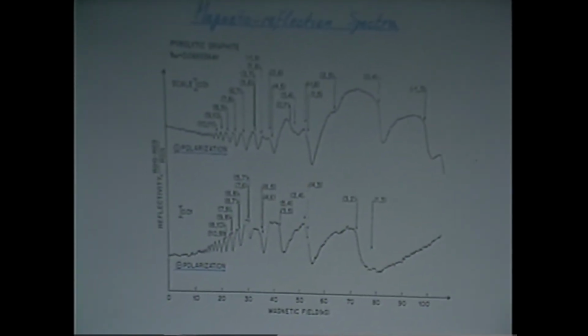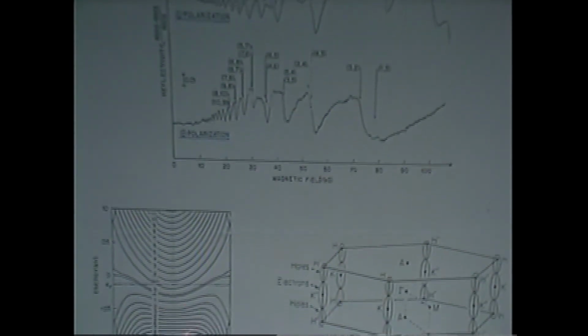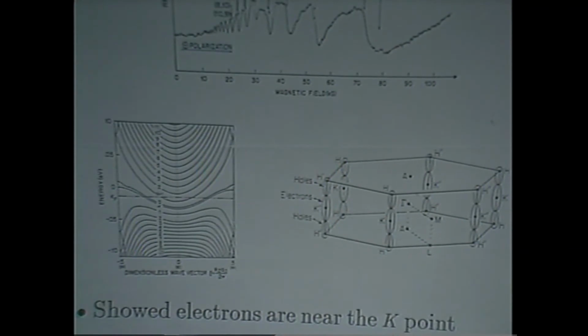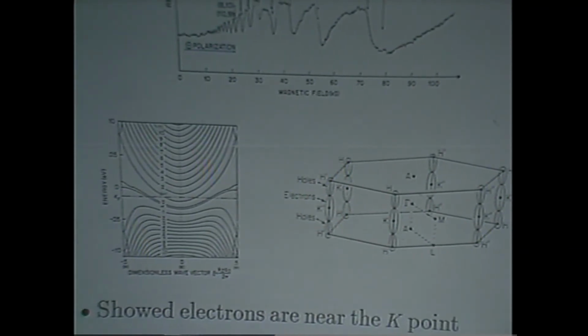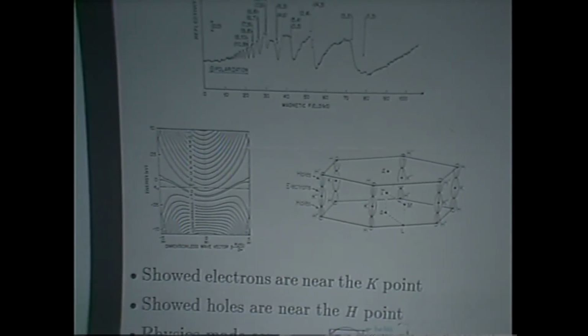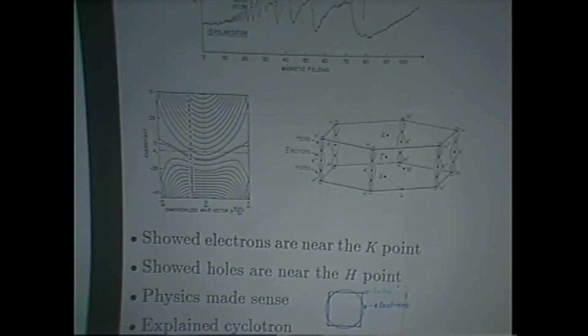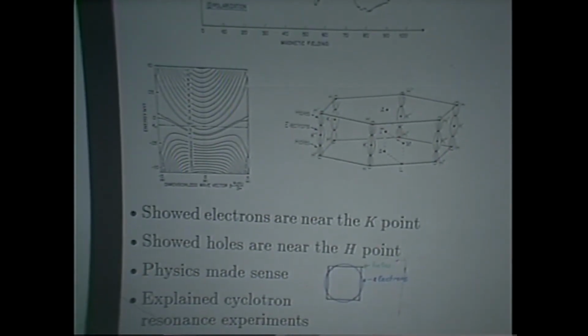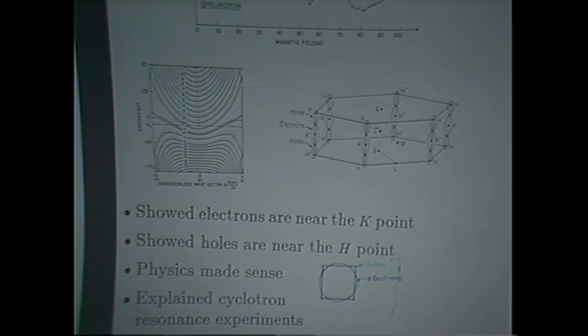So here's a spectrum with two different polarizations, and you could see lines here, and the indices go up, going from the valence to the conduction band, and with this polarization they go down. So it's clear that one can tell whether the spacing of the Landau levels in the valence and conduction band is bigger or smaller, and we use that fact to turn the energy bands upside down. Now, we knew we were right for other reasons, that this whole thing made physics sense.